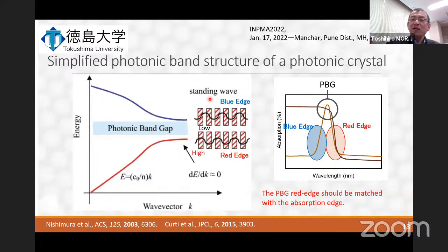This figure represents a schematic drawing of the simplified photonic band structure of the photonic crystal, as you have seen before. We will check again the location of both the photonic band gap and the absorption edge here. At the red edge, group velocity of light decreases and the photon can be captured like a standing wave, and its highest amplitude is localized in the material part here. At the blue edge, the standing wave is predominantly localized in the void part. To suppress electron-hole recombination, the absorption edge of the material should match the red edge of the photonic band gap. It's better, I think.